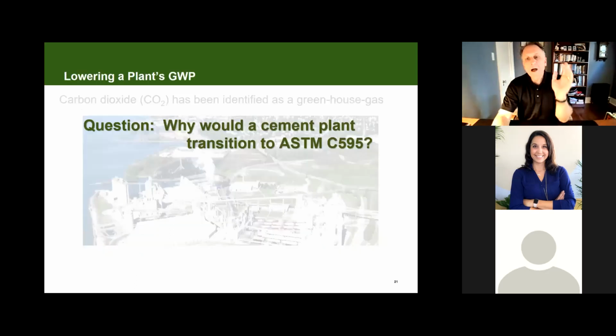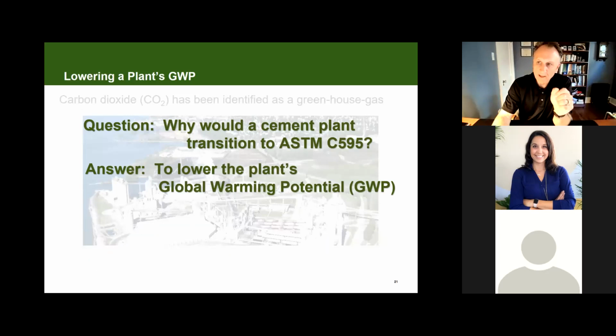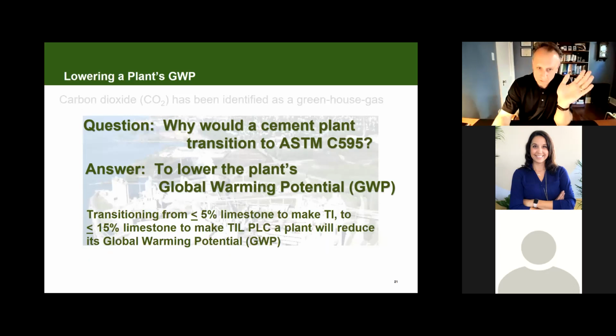So again, why would a cement plant transition to ASTM C595? To lower the plant's global warming potential. We definitely got to have that down pat. And so transitioning from 5% limestone, which we've done for many years to make type 1, to less than 15% limestone to make a type 1L PLC, a plant will reduce its global warming potential. And I repeat that because this is the thought process, if you will, to hopefully get us out of the crosshairs and get us out of these headlines that I read earlier. Okay.